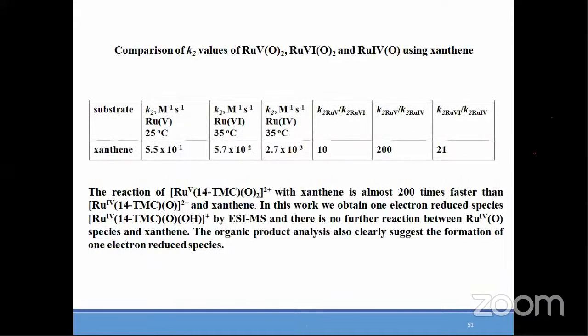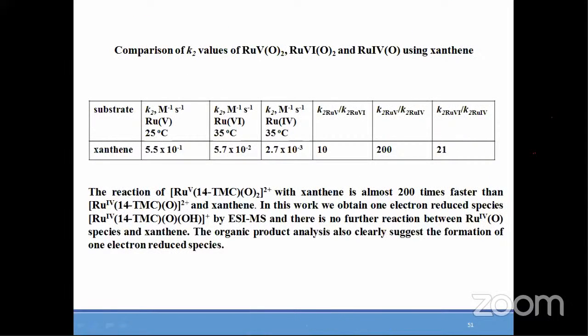When you compare the reactivity of the ruthenium(V) oxo species with the ruthenium(VI) dioxo species, you can see here the reactivity of ruthenium(V), ruthenium(VI) and ruthenium(IV) species. What we notice is that the ruthenium(V) species reacts very fast with xanthene. When we compare ruthenium(V) to ruthenium(VI), the reactivity is 10 times. When we compare ruthenium(V) to ruthenium(IV), the reactivity is something like 200 times. And when we compare ruthenium(VI) to ruthenium(IV), it is something like 21 times. This work is not yet published, so hopefully we are going to publish it.